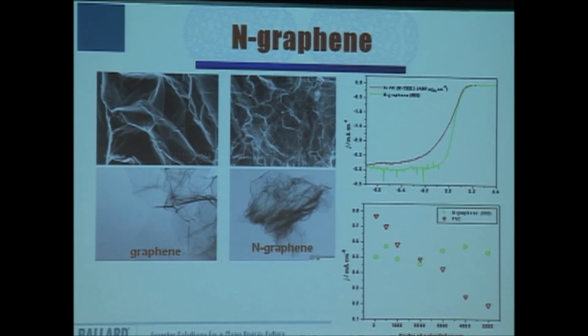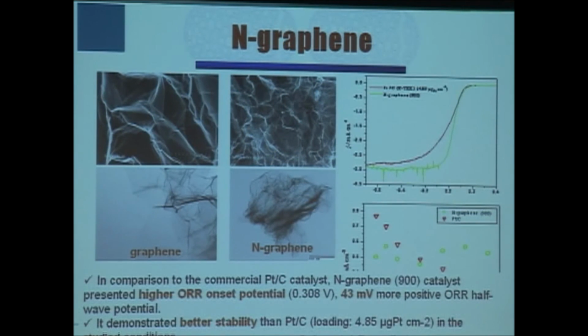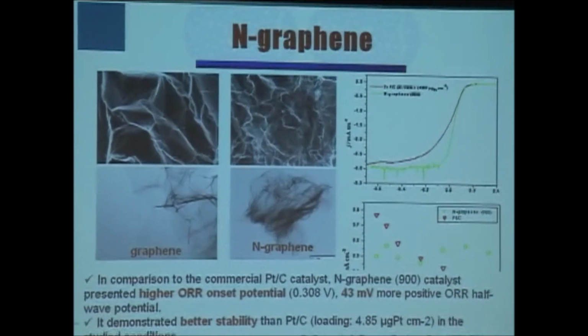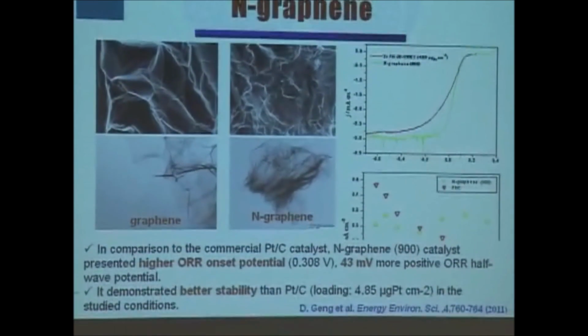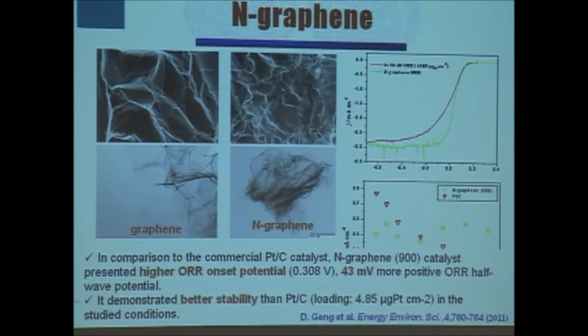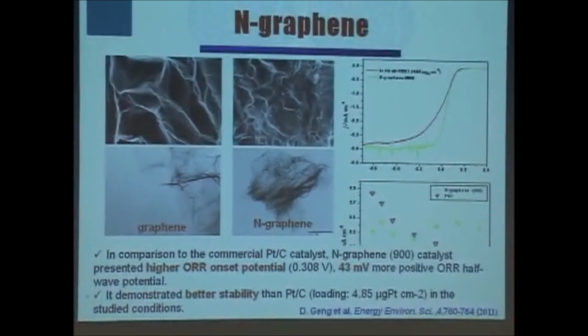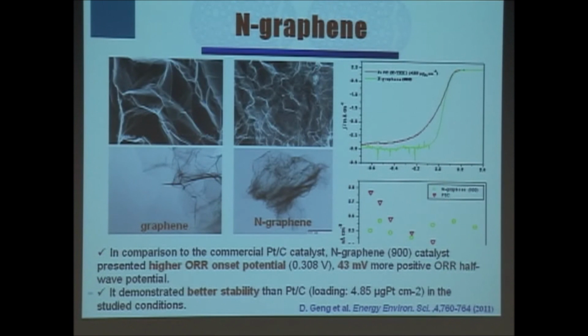Since this is a very preliminary result, maybe you can argue that this zero time is a little bit in conflict with that. However, this was tested under different current density. Talking about the performance, we're mostly talking about onset potential. This platinum-free catalyst is even better than platinum catalyst. Also, it demonstrates better stability. This is still a very preliminary result. We need to work further on that.